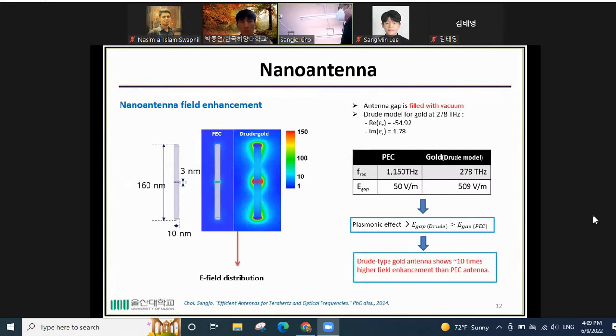And this is the comparison of field enhancement between PEC, perfect electric conductor antenna, and Drude model nano antenna. From this, you can see that the Drude model nano antenna has a higher electric field enhancement compared to the PEC because of the negative permittivity of the antenna and low conductivity. That's why in this field enhancement, the Drude model nano antenna shows 10 times higher field enhancement compared to the PEC antenna.